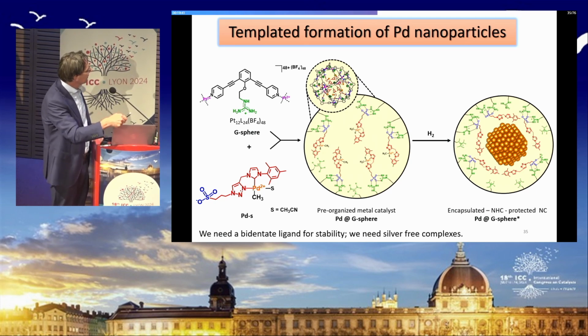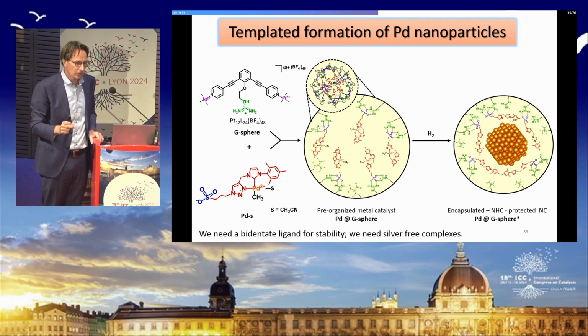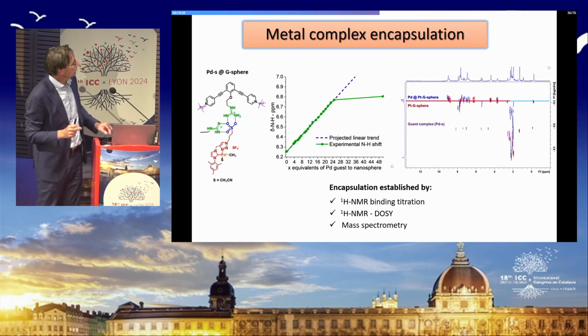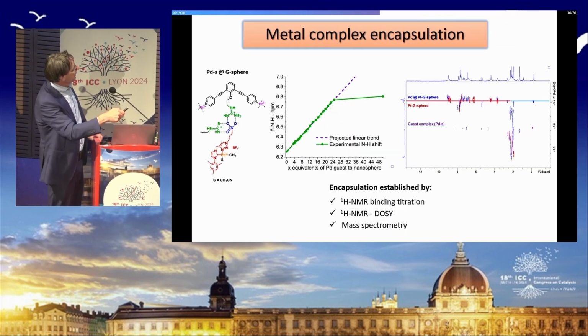An important note is that these types of palladium complexes need to be prepared silver-free, because if it still contains silver, we form palladium-silver alloys. Also interesting, but maybe for another time. So here is again the titration data, where we can titrate in up to 24 of these complexes in the cage, and after that it levels off.